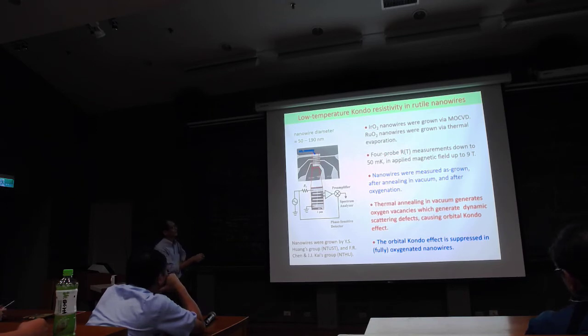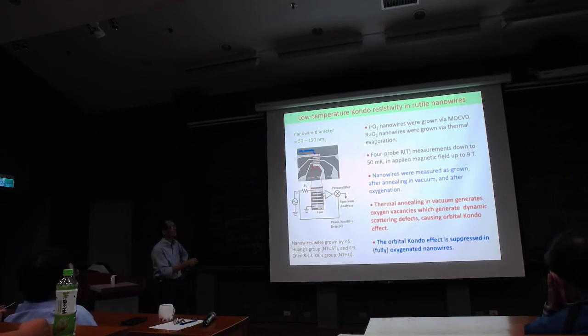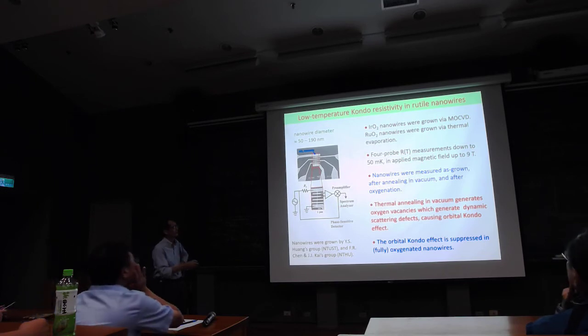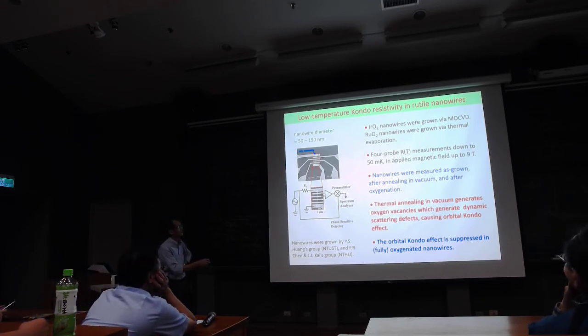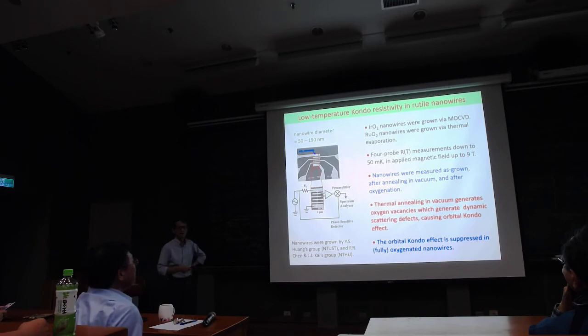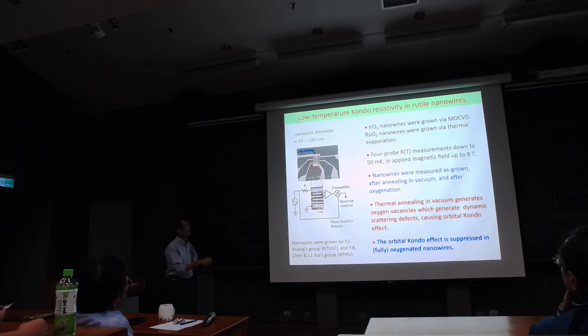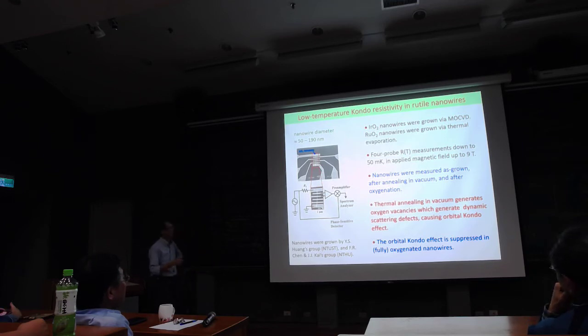So we have these nanowires and we do four-probe measurements down to 50 millikelvin, and in magnetic field up to 9 tesla. Application of magnetic field is very important because once you apply a magnetic field, if there's a big change, that means a magnetic moment is there. If no change, it implies that there's no magnetic moment. So we apply this.